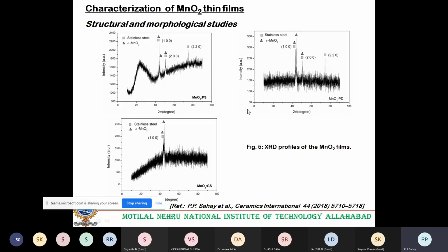So here in this case, this is the XRD profile. Here you see this square one, this is the stainless steel. This triangle is for epsilon MnO2, and this is the film prepared by potentiostatic, this is from potentiodynamic, and this is galvanostatic. Now you look here, you will see that the stainless steel peak and the MnO2 peak are coinciding at the same point. Here in this one the peak is coming clearly, but here it is coinciding. This is for 220 stainless. This is the stainless peak, but here it is coinciding. Here also coinciding. So a confusion is created in the mind whether this peak is from stainless steel or MnO2.